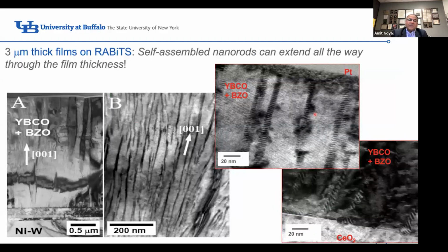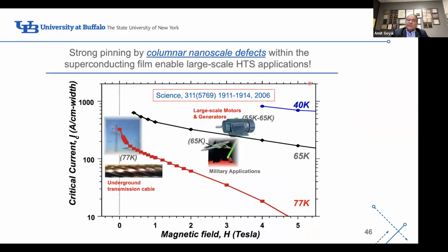Next, we made these films. We made them very thick. We can make them all the way up to 3 to 5 microns with no microstructural degradation. The nanocolumns start from the interface of the buffer layer. They go all the way to the top. And then we finally have a performance.